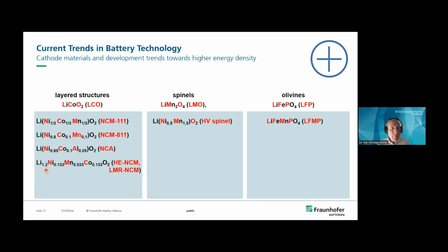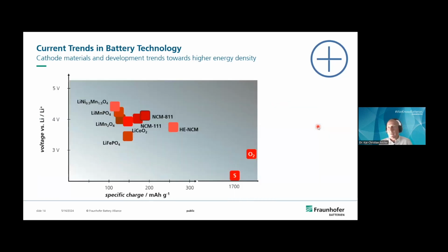You see here there is more lithium inside and the specific capacity would be higher. For the spinels, we have the possibility to go to higher voltages, as shown here with the high voltage spinel. And with the olivines, they don't have such a high voltage, so it's more or less a lower capacity in the batteries. But this can be improved by the addition of a manganese to the so-called LFMP material. All these can be seen here, where we have the specific charge here. The high energy NCM gives the best specific charge, and the best voltage would be the high voltage spinel.